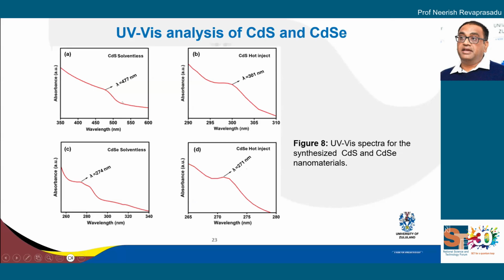You see for the solventless route we have 477 nanometers, but for the hot injection we have much smaller particles at 301 nanometers. So you can actually determine the size, which is not very accurate, from the Brus equation that I showed you, using the absorption maximum and band gap. And this is cadmium selenide, again giving you a good, sharp band edge. And then this is for the solventless route, which is much larger.